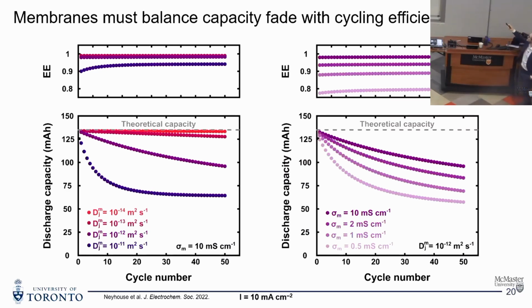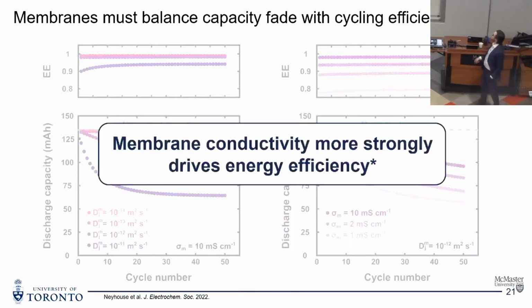And the reason is that as we go to lower conductivities, to push the same amount of current, we need to generate a larger electric field across the membrane. We get a larger voltage drop. And that larger electric field provides a larger driving force for ions, forcing them to cross the membrane faster at the same applied current. So we see all of these trade-offs, and we make maybe a general conclusion that membrane conductivity more strongly drives our energy efficiency, right?